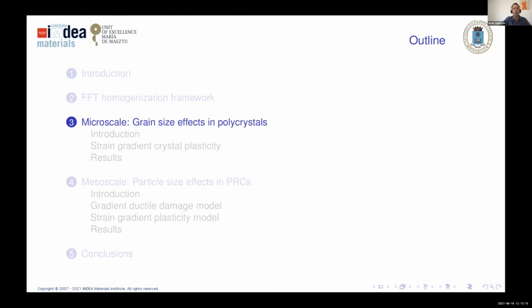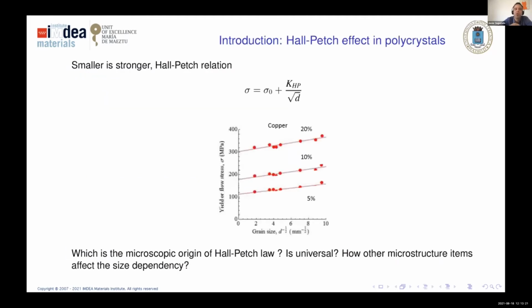The first one, as I told you, is on the microscale, and we're interested in using this technique to obtain grain size effects in polycrystals. The grain size effect is a very old and well-known problem, and there is a very well-known relation that is written here. That is the Hall-Petch relation, which tells us that the flow and the yield stress are related to the inverse of the square root of the grain diameter. This law works well experimentally, not exactly, because this exponent is not exactly 0.5, but it works more or less properly for many, many materials.